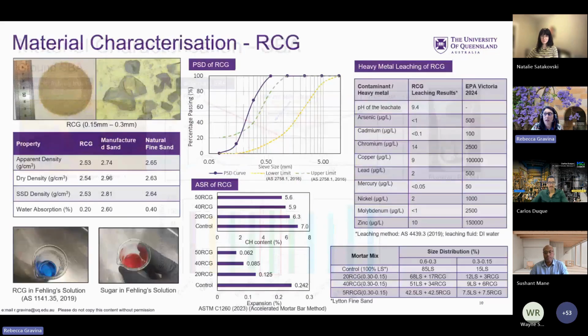In terms of the recycled crushed glass, this is some of the results that we have achieved in terms of the characterization for the apparent density, the dry density, also the water absorption properties, and how that compares between the recycled crushed glass, the manufactured sand, and the natural fine sand.